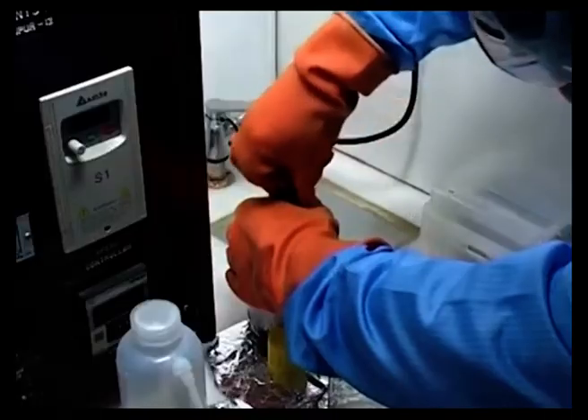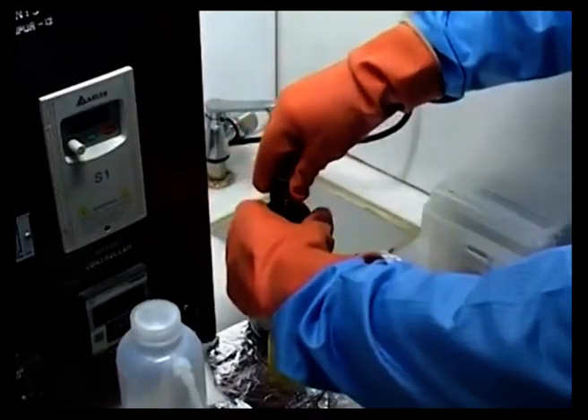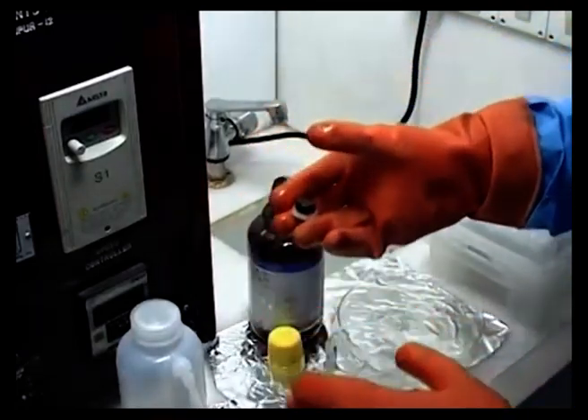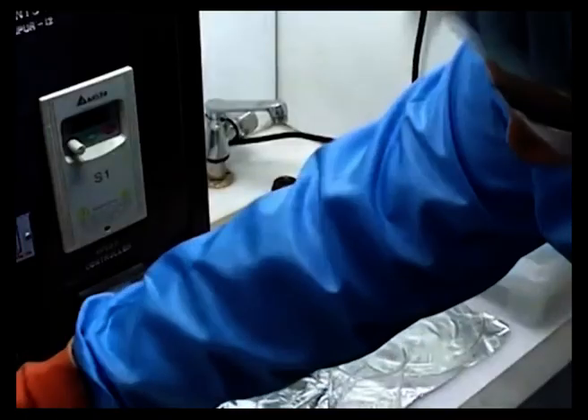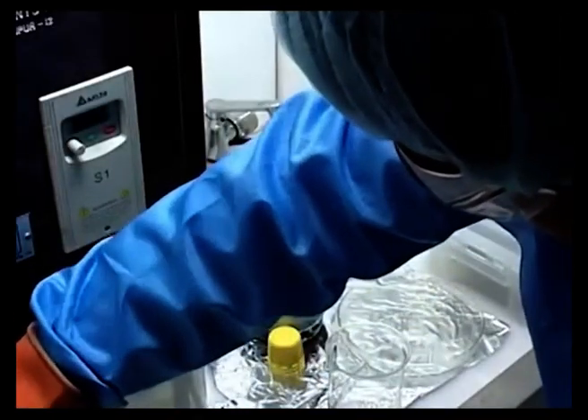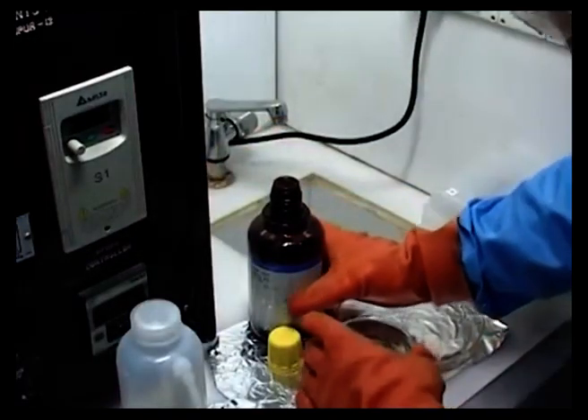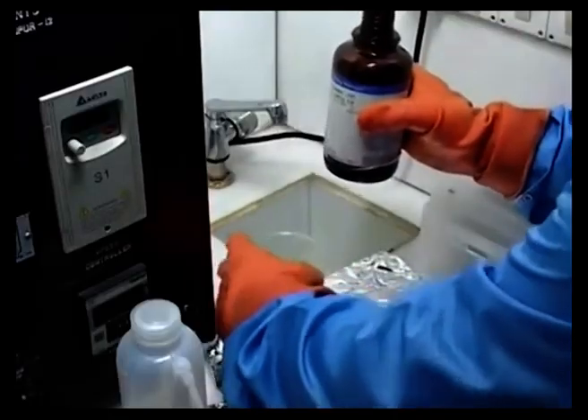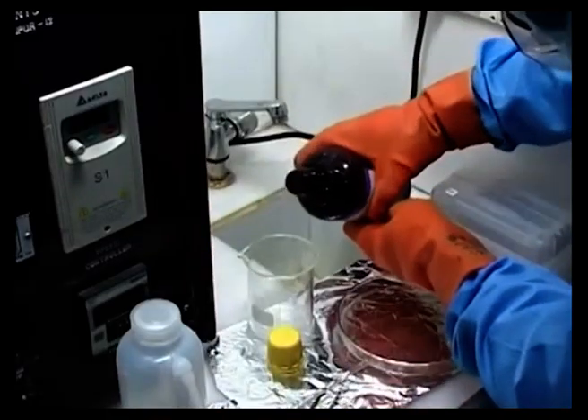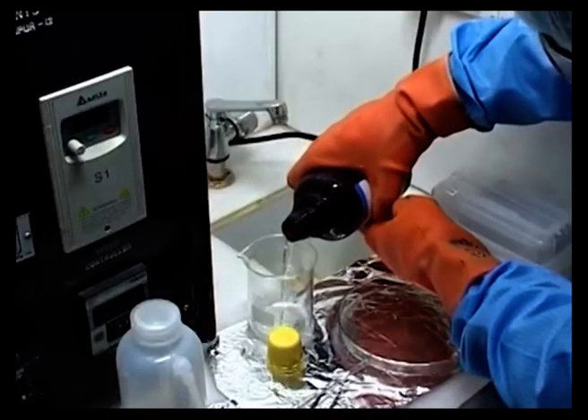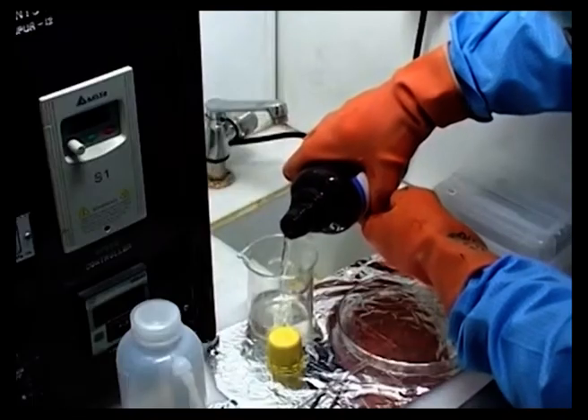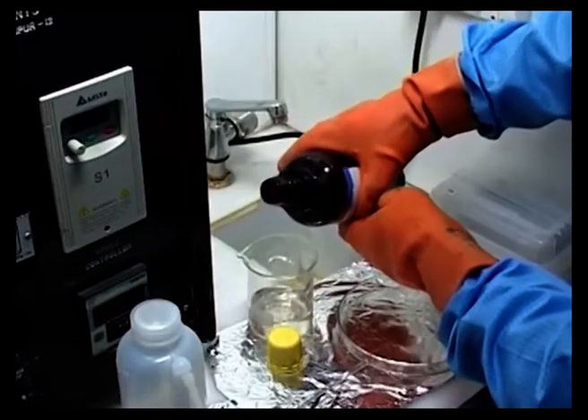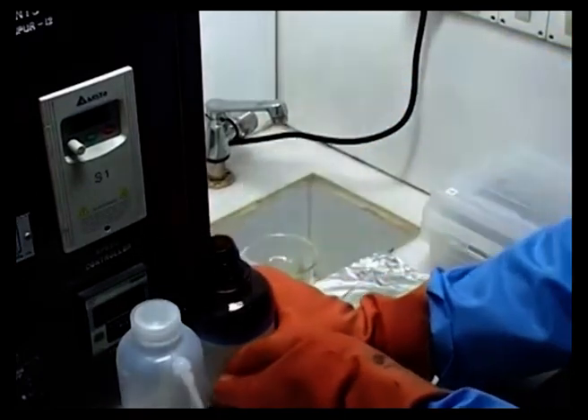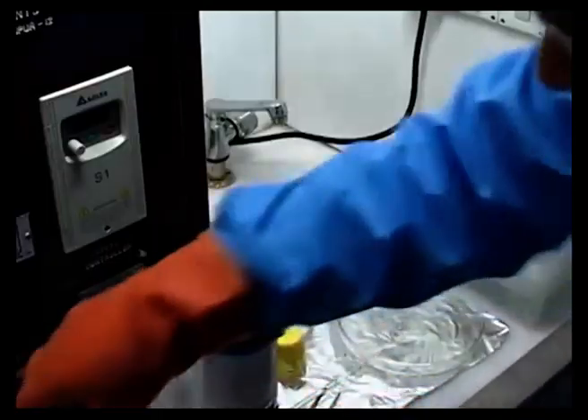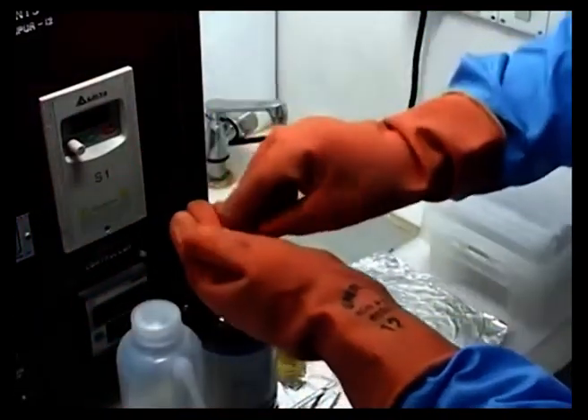You use these gloves. So basically you open the acid bottle and keep the cap in a safer area, and essentially now what you do is take this bottle and pour it in this beaker here very carefully and very slowly. As you're seeing here, pouring this is not a very easy job. Do it just about close to 100 ml. Okay, and essentially again keep this back in its place, cover this properly so that there is no chance of any spillover, and essentially close the lid.